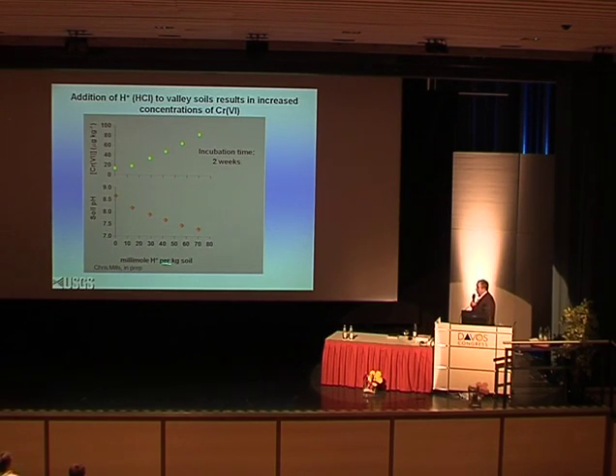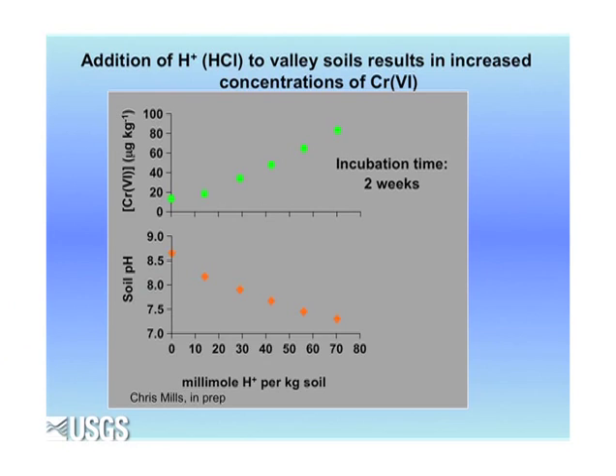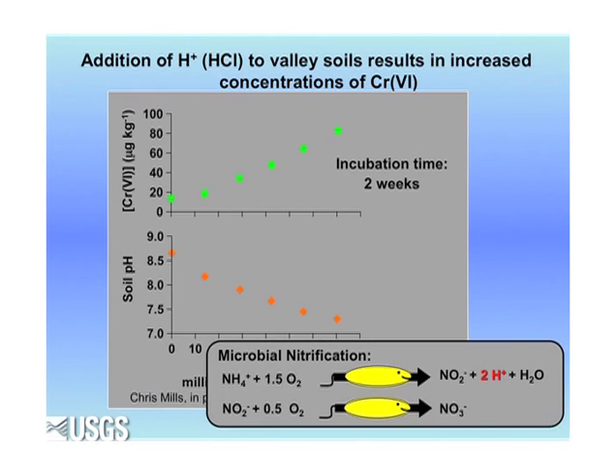That factor appears to be pH. So this is added protons as HCl per kilogram of soil, incubated for a constant 2 weeks, showing increase in chromium 6 over that time period. So hydrogen ions are important. So the hypothesis we're working on is that a big source of the protons necessary to drive rates of chromium 3 oxidation higher is nitrification, in which ammonia reacts with oxygen to produce nitrite and protons.